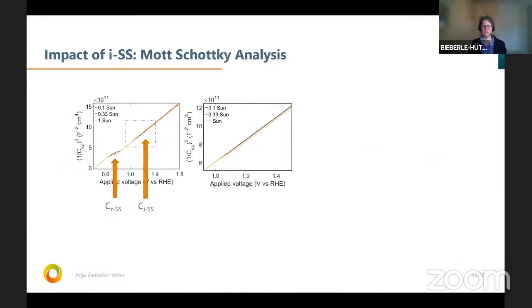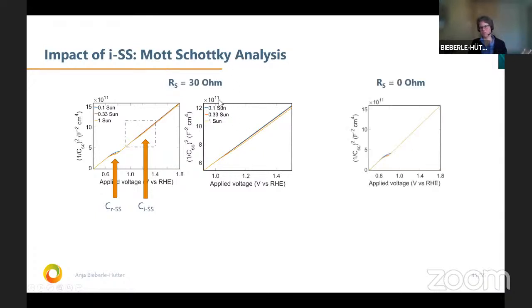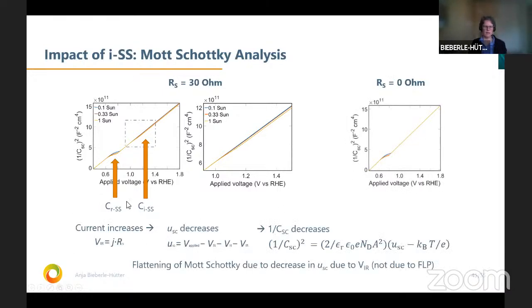So therefore, we see that the difference here is not so huge, because the reaction sites itself are not changed so much. Also, a nice result from the Mott-Schottky analysis is that we have this Fermi level pinning for the recombining surface states. Here for the ISS, we also see a decrease. And sometimes in the literature, this is interpreted as a Fermi level pinning. But actually, when you look with 30 ohms series resistance, you have this, but with 0 ohms, you do not have this.